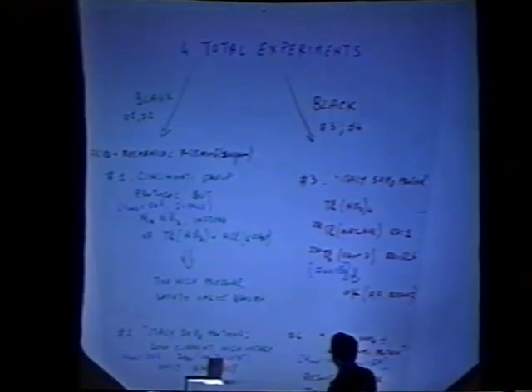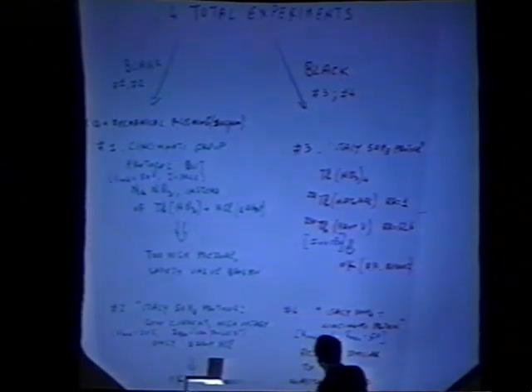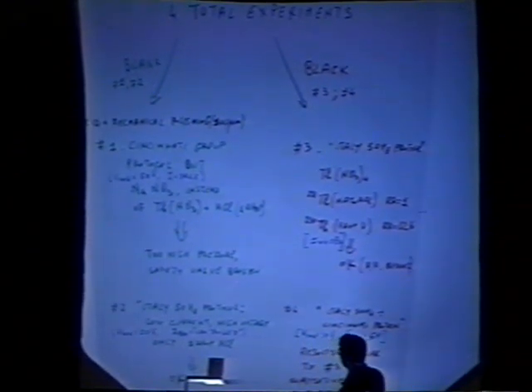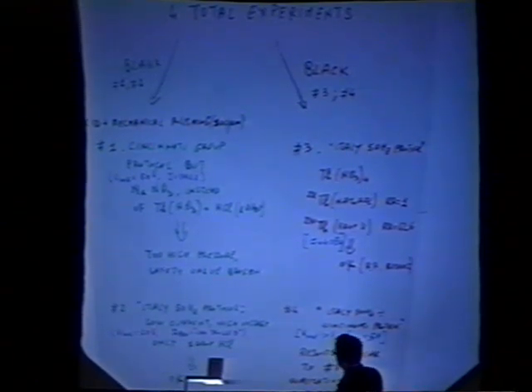The third was the Black experiment. So in the third experiment, we followed the protocol we have found safely and used thorium nitrate. In our condition, we don't have only natural thorium-232, but from the point of view of radioactivity, we have a big amount of thorium-230 coming from uranium decay.